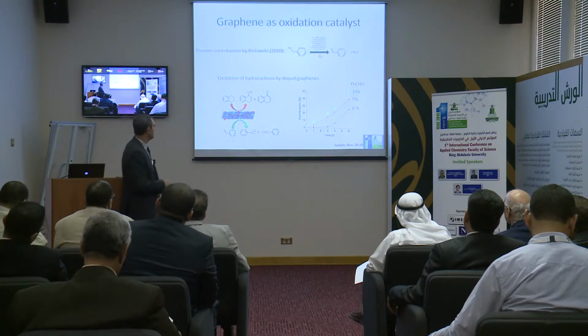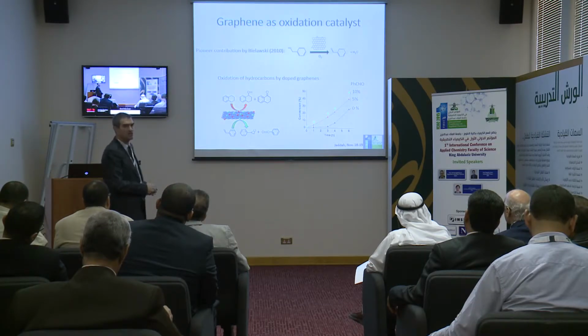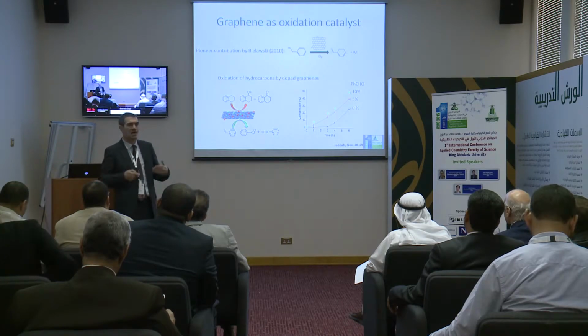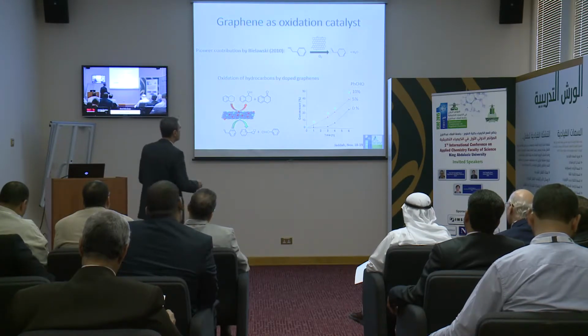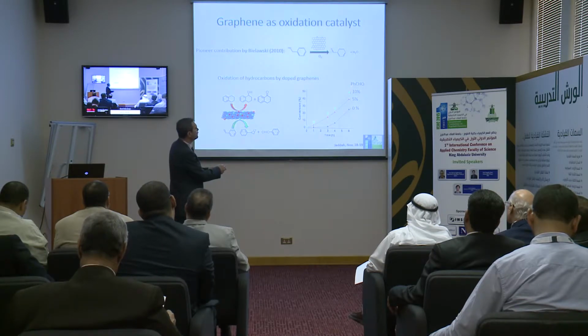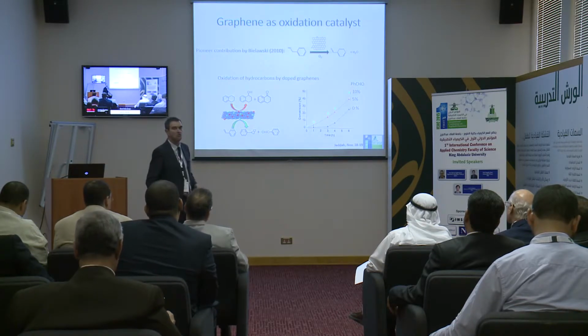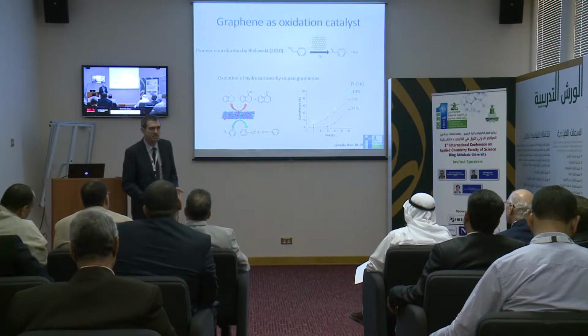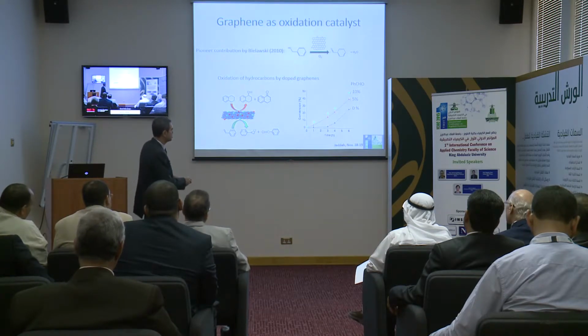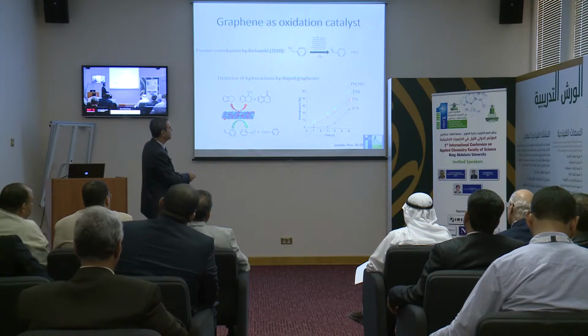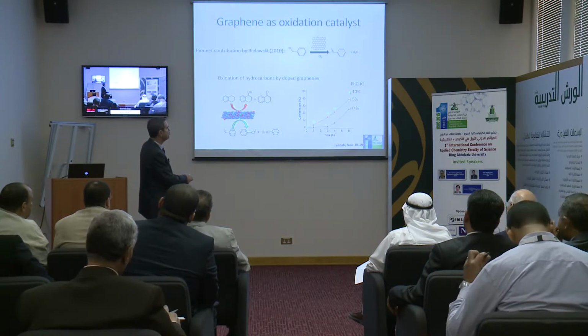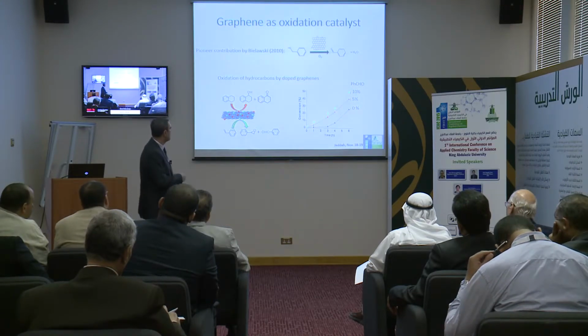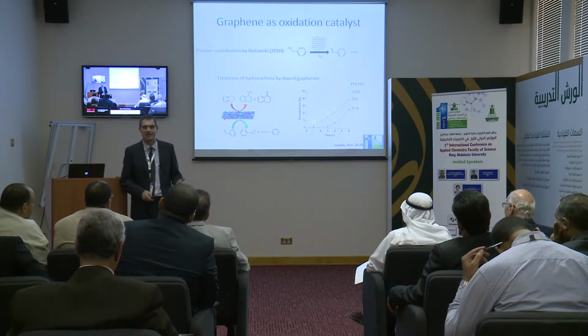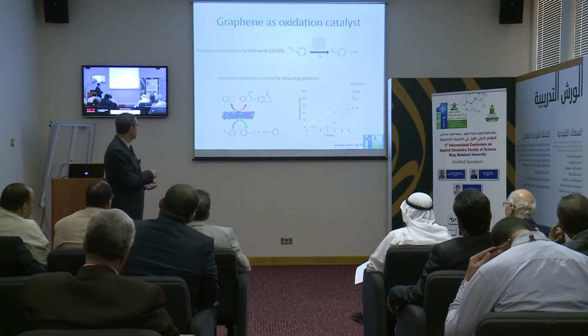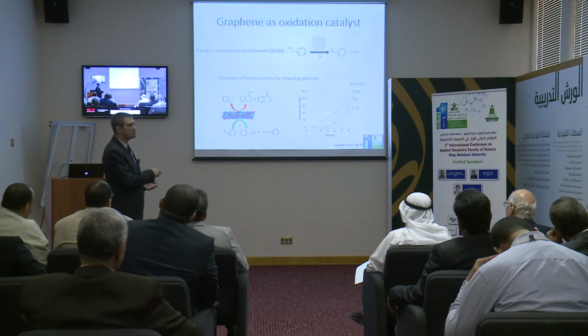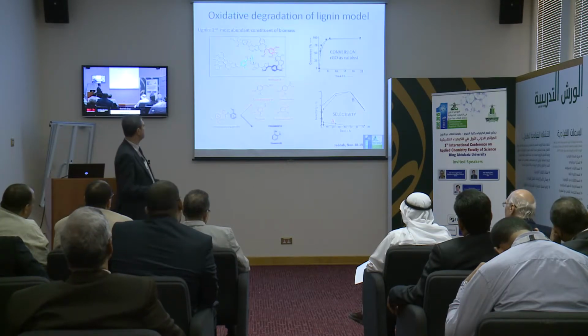But what we notice is that as soon as benzaldehyde is formed, then the reaction starts and becomes accelerated. So we made an experiment in which we on purpose added benzaldehyde, because it's known that benzaldehyde in combination with oxygen can promote radical reactions. And by adding benzaldehyde at the beginning of the reaction, what we observed is that the induction period disappears. So really, we have other evidence that shows that the role of graphene in these reactions with oxygen is just to generate the first radical.